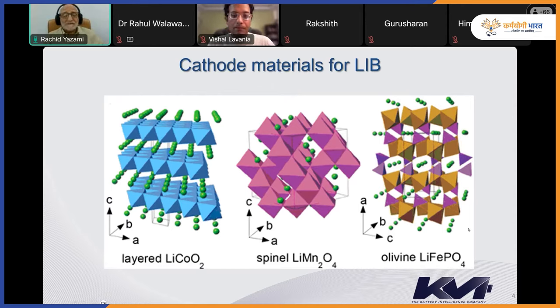And for the lithium iron phosphate based battery, the average voltage is about 3.3, or 3.2 to 3.4 volt. So it's lower than the layered oxide and the spinel metal oxide. And for this reason, the LFP-based lithium-ion batteries have a lower energy density. Energy density is expressed in watt hours per kg.